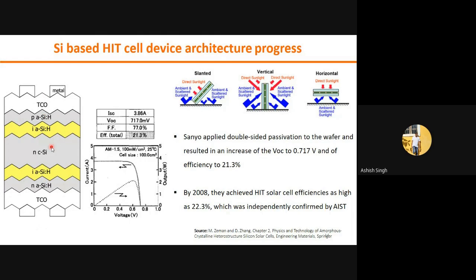And if you notice, the cell looks exactly symmetrical from top to bottom. If you see the top side, amorphous silicon, p-type and TCO, this side is also the same, so it won't give stress in the film, so that we can use ultra thin silicon wafer for the device fabrication. And the advantage of this device is we can install in any direction, like slanted or vertical or horizontal.